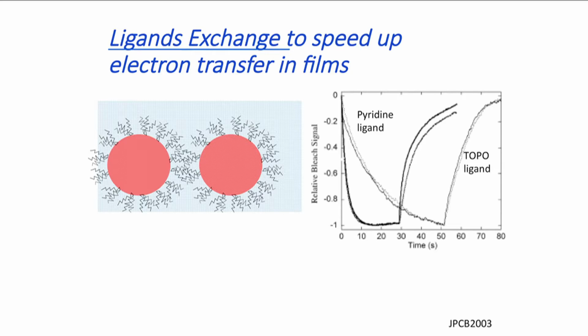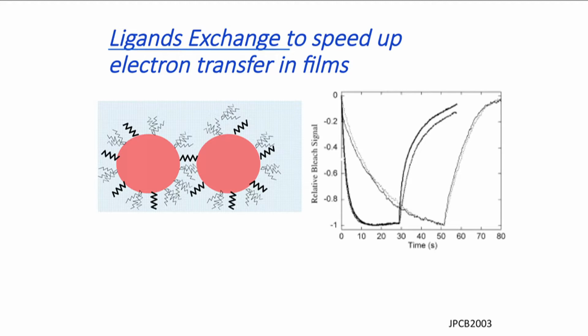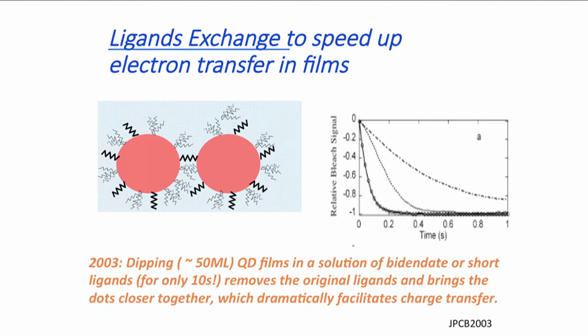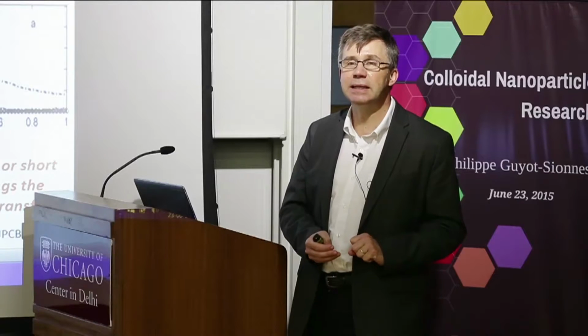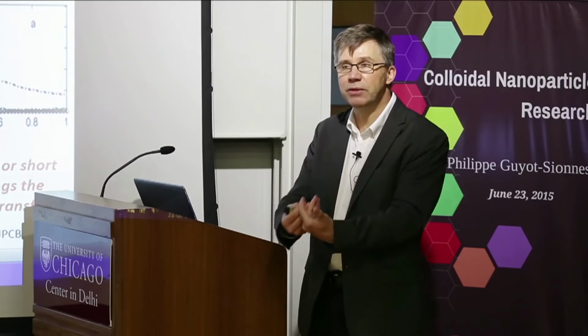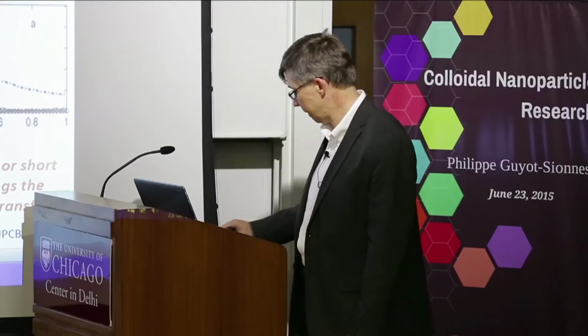And then we realized something very simple. We just changed the distance between the particles with a small ligand, and that was done in a very simple way, simply dipping those films into a solution, and you find that the response time drops by about 3 orders of magnitude. So now, instead of being tens of seconds, it's tens of milliseconds. So that was the first hint that if charge transfer can be that fast, so that the film can change color in tens of milliseconds because of charge injected all throughout the film, then it might be conductive.